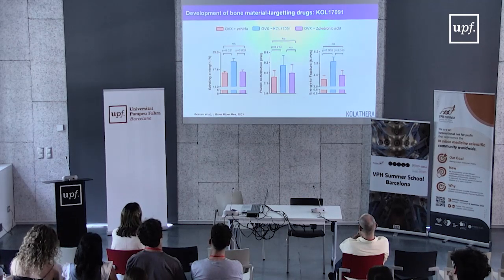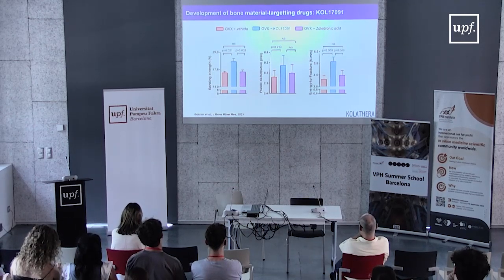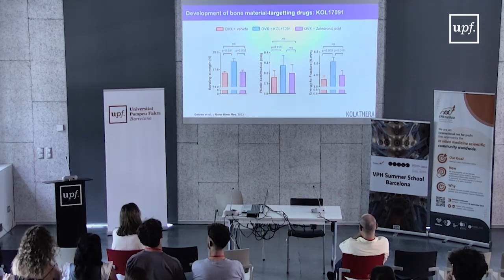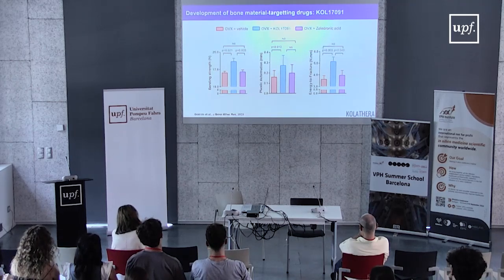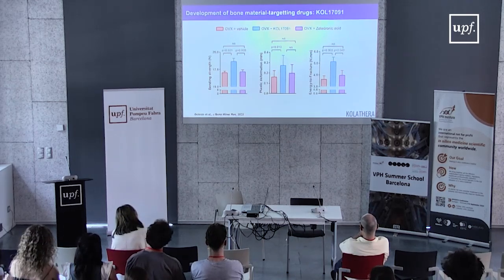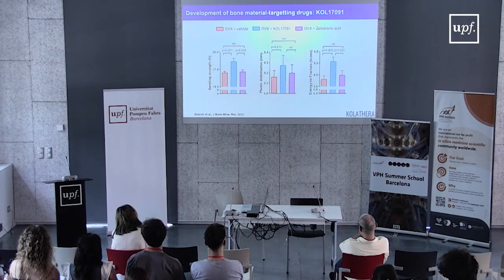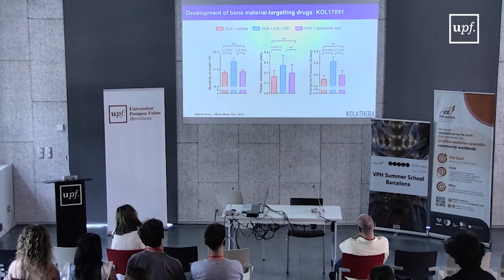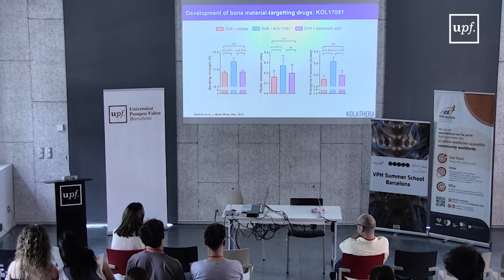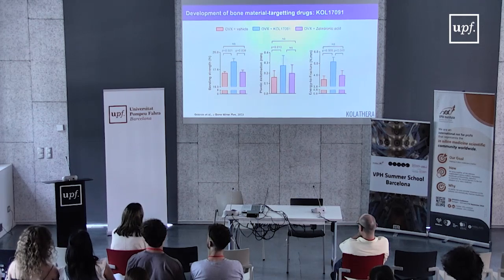And when we do that, it's actually enough to increase the mechanical resistance of the bone, and especially to increase the bending strength and the toughness of the bone, with the plastic deformation and the energy which is required to break the bone matrix. And we're doing this with KOL in a much better way than with zoledronic acid, which is the most often used molecule today in the anti-osteoporotic arsenal.